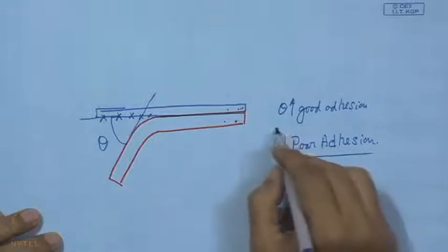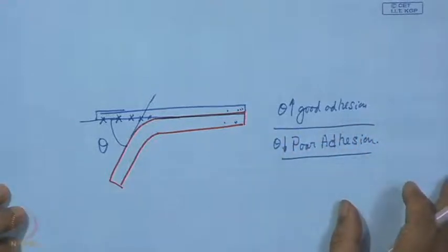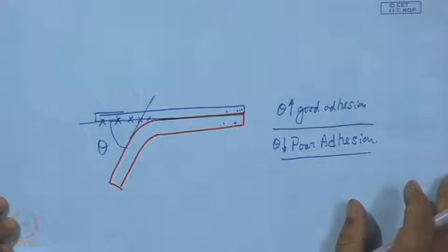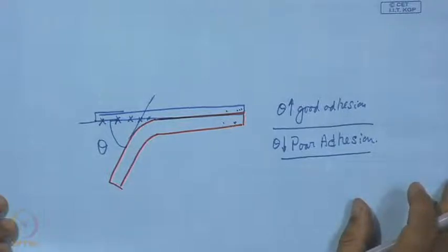This is one way of assessing the coating — theta can be accepted as an index of adhesion. However, it does not give any impression of the actual force or strength of adhesion; it can only rank coatings in terms of adhesion, and the scale of theta serves as a guiding index.